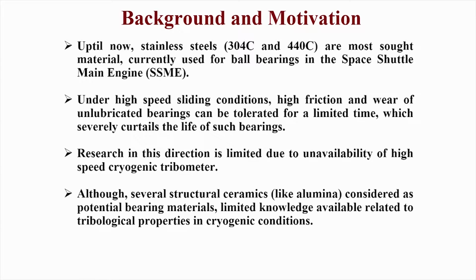As I have categorically mentioned in one of the earlier lectures, 440C martensitic stainless steels or 304C stainless steels are mostly sought materials currently used for ball bearings in space shuttle main engine. Under high speed sliding conditions, high friction and wear of unlubricated bearings can be tolerated, but it severely curtails the overall life of the bearings.